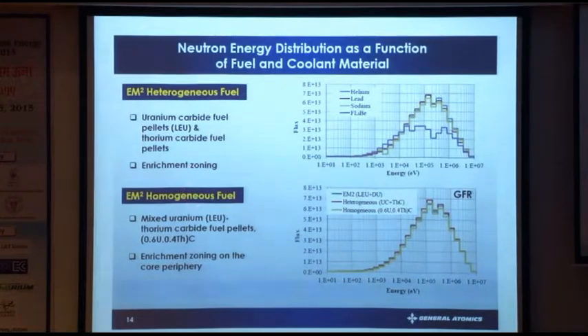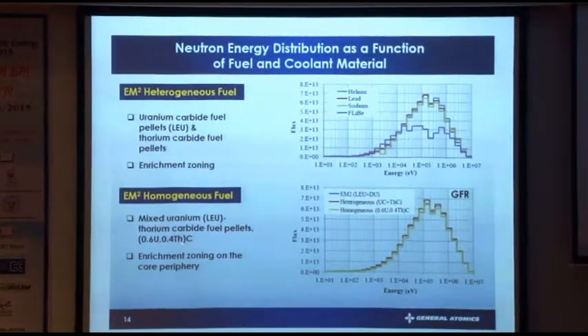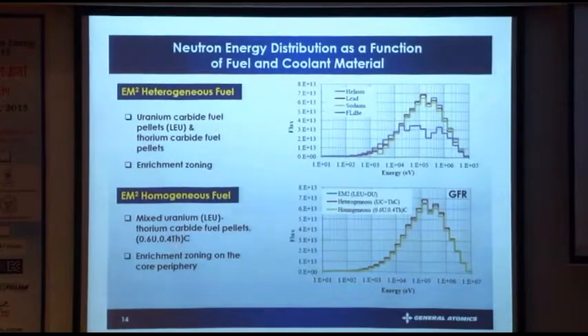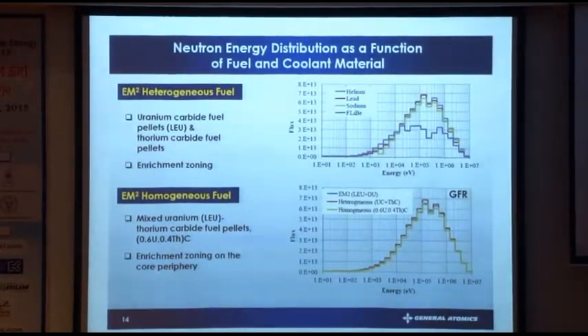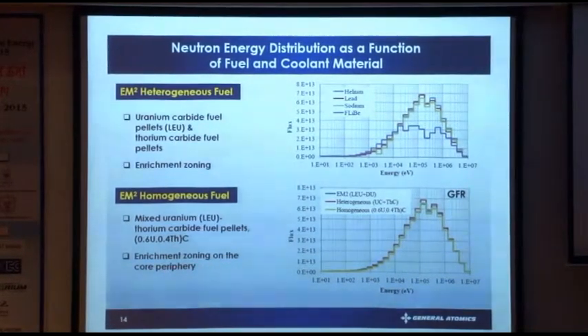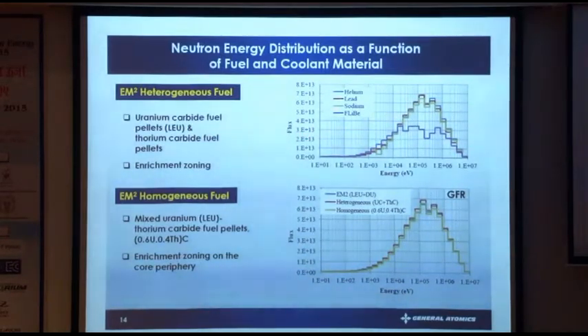In the homogeneous one, on the other side, we looked at mixed uranium thorium carbide fuel pellets. Here, it's 60% uranium and 40% thorium. And there is enrichment zoning required only in the core periphery. Then what we have looked at, for these heterogeneous cores, if all else remains the same, the loading remains the same, then we look at the sensitivity of neutron economy to various coolants.